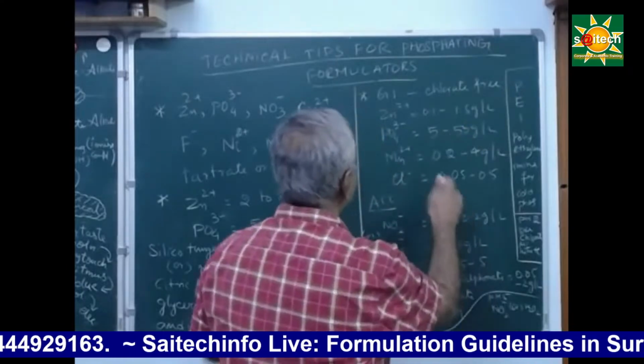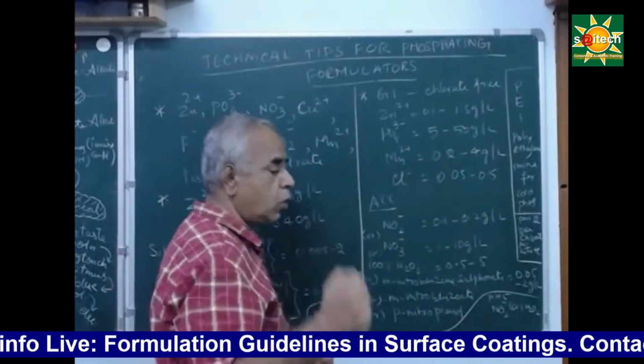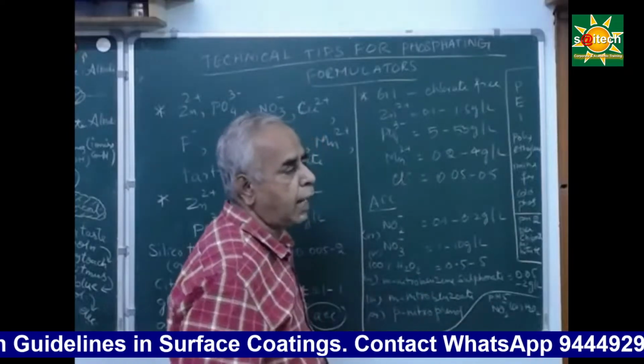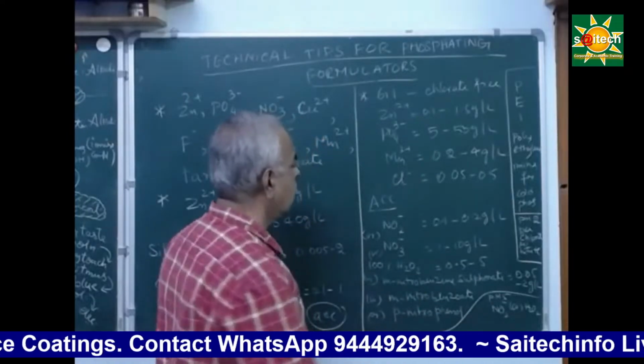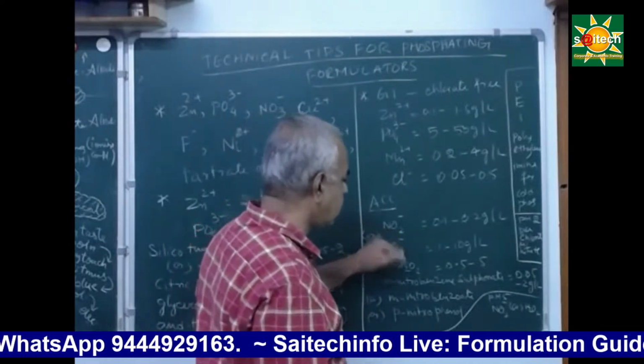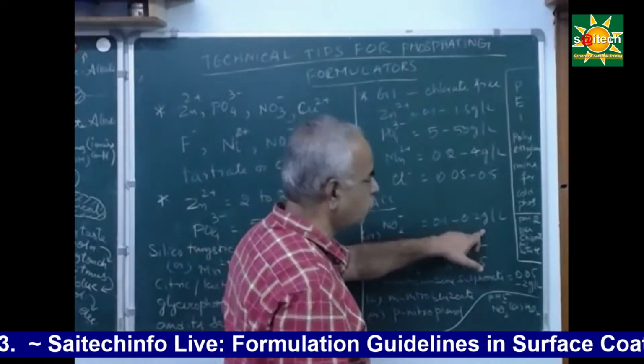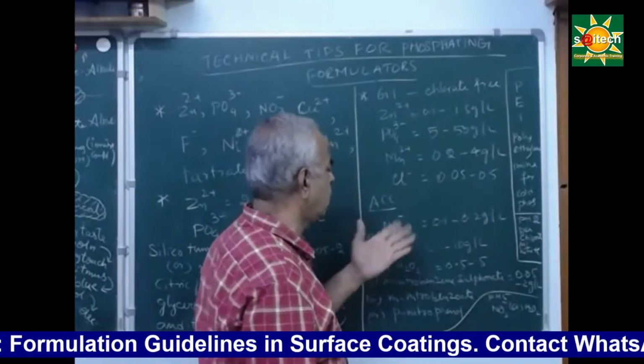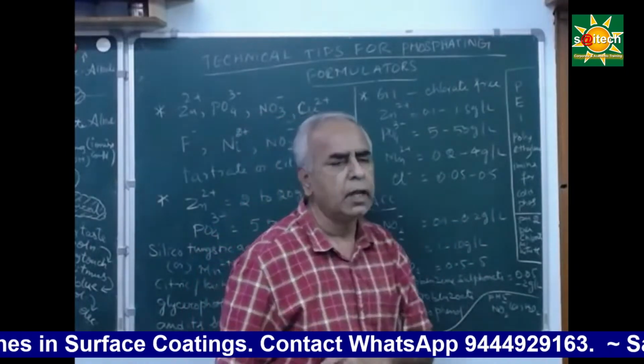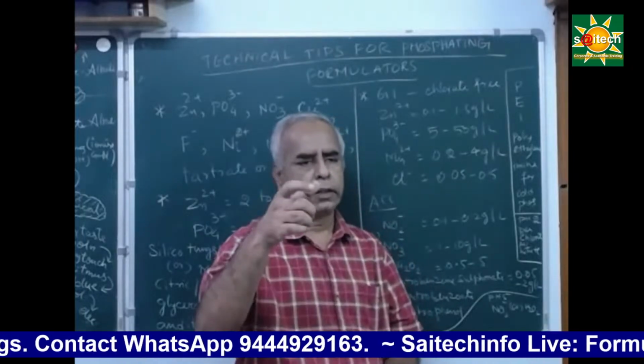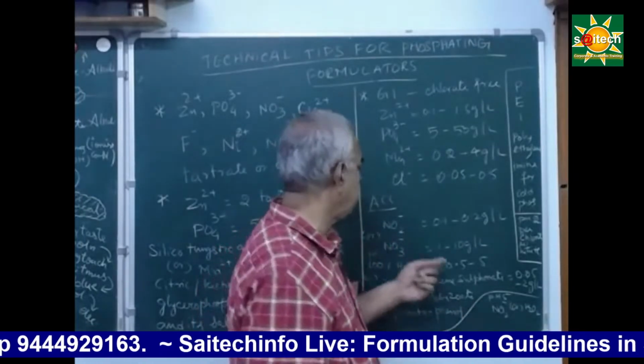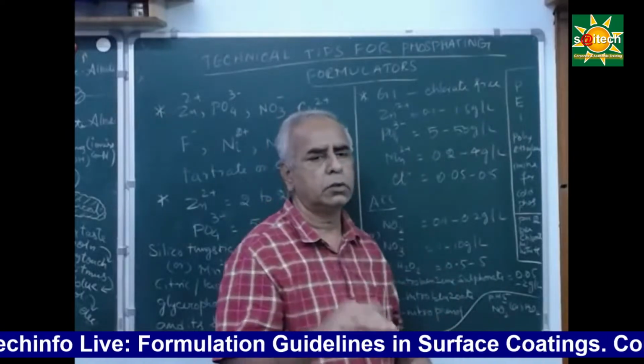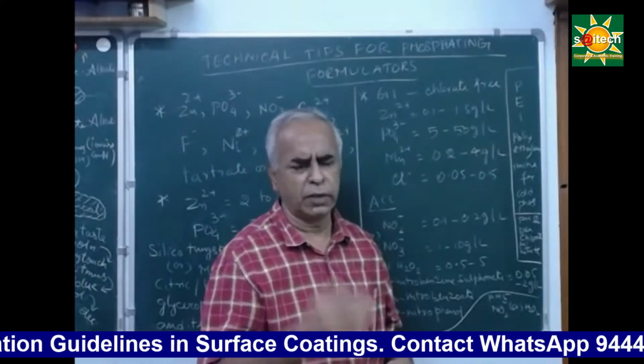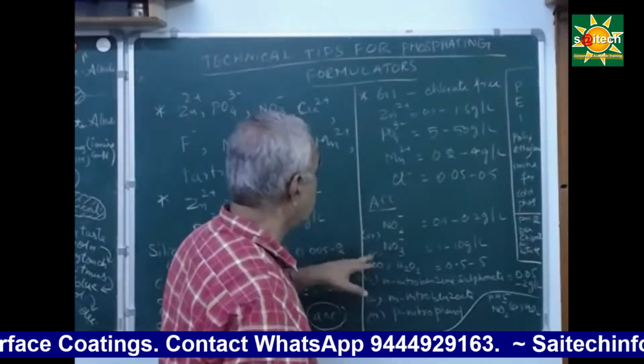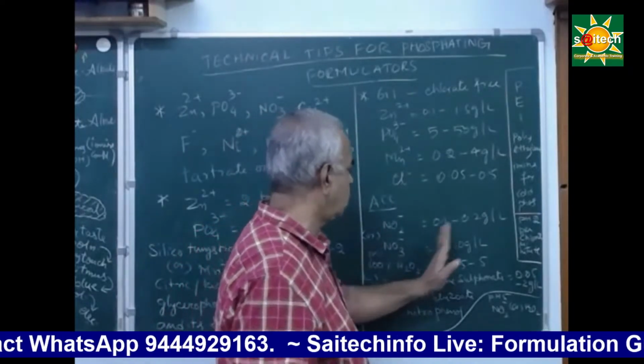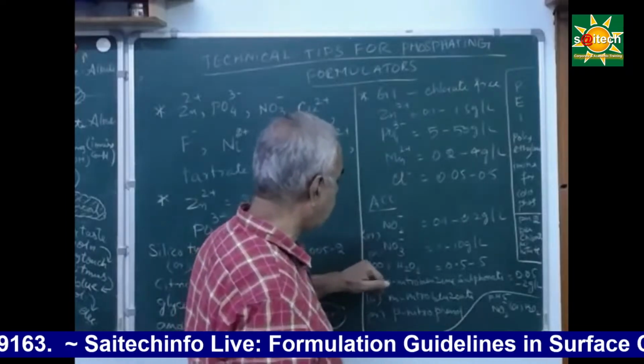These are all tentative formulas, and as I already suggested, you have to supply the accelerator always as a separate pack. Here the accelerator nitrite is 0.1 to 0.2 gram per liter. You can easily work out this formula. You simply take sodium nitrite and dissolve it, so if you take 1 liter, the nitrite content should be 0.1 gram to 0.2 gram. It's a very simple formula. And then nitrate should be how much? 1 to 10 gram per liter, or you can add 100%.